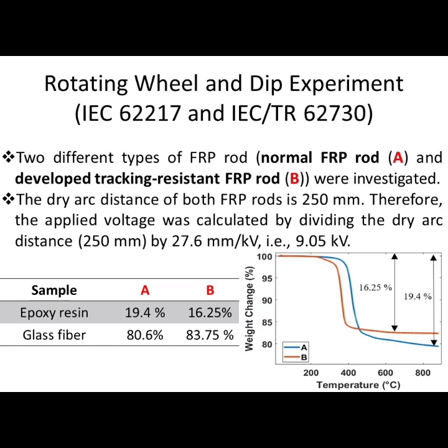Two different FRP rod samples were used in this experiment. The first one is the normal FRP rod, and the second sample is the newly developed tracking resistant FRP rod, which are provided from the manufacturer. The applied voltage was based on the dry arc distance, which was about 250 mm for both samples, and the applied voltage was about 9 kilovolt.